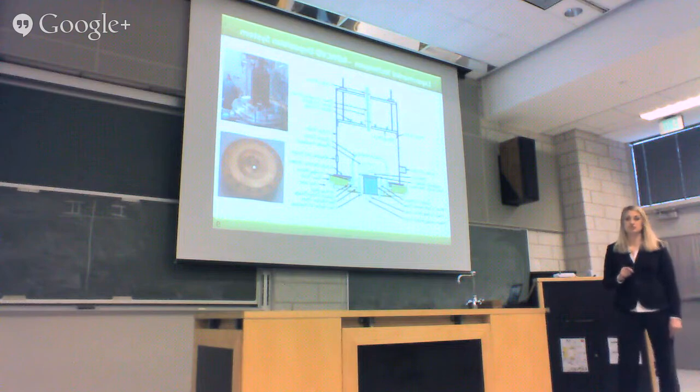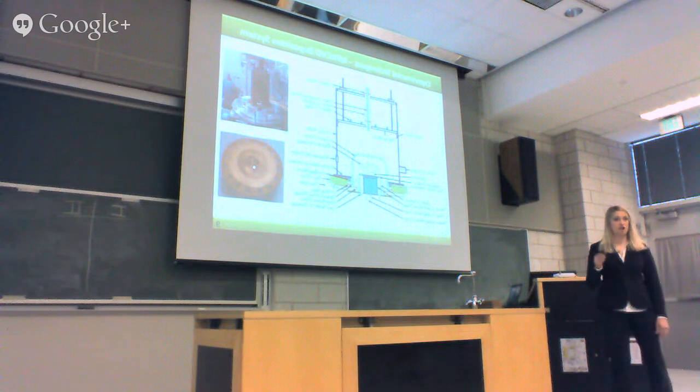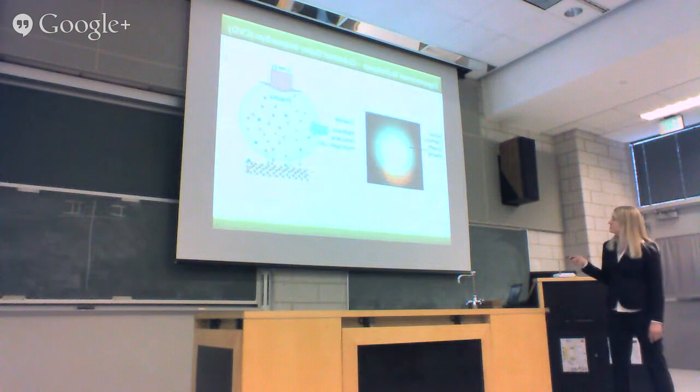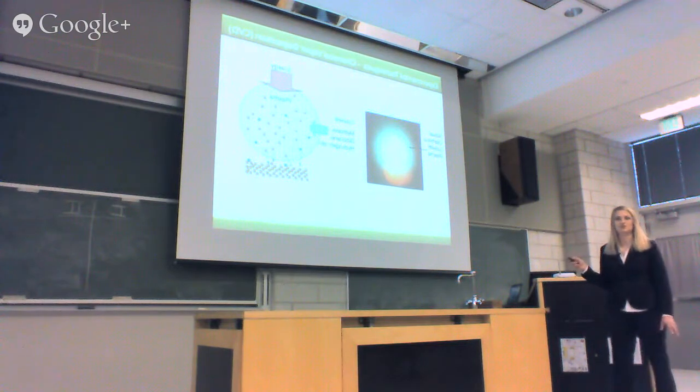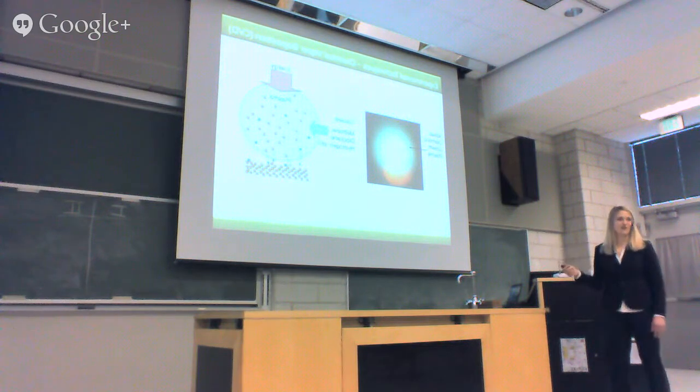That's hydrogen, to eliminate the nucleation of graphitic phases, and methane, which acts as our carbon source. In our case, because we're boron doping, we also include a boron source, which is diborane. So the actual process looks schematically sort of like this. We have energy that comes in and creates a plasma, and then gases come in that get split into more reactive species that then add a little bit at a time onto the diamond surface. In this case, the blue is supposed to be boron, and the yellow is supposed to be carbon as it gets added, essentially one atom at a time.